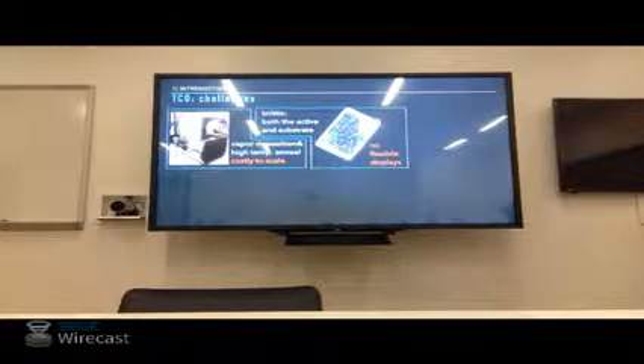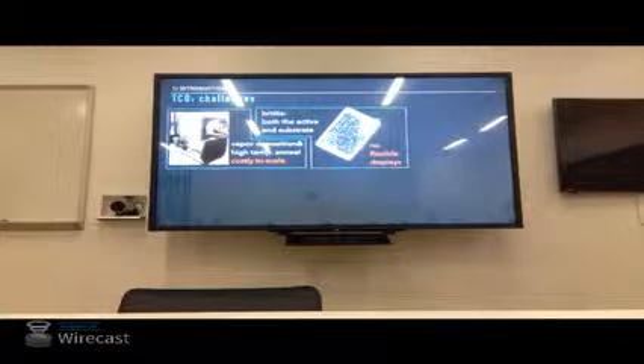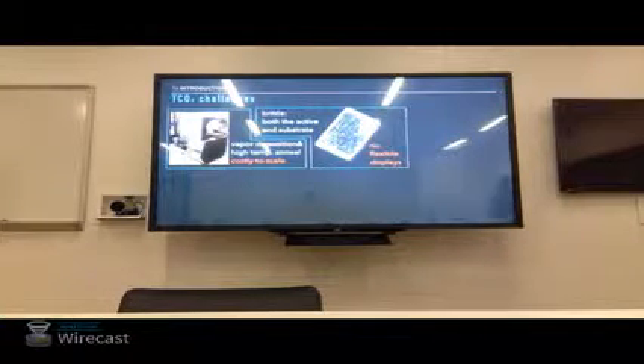As well, they're brittle, and this is mostly because, to have an excellent substrate for these things that handles high temperature and high vacuum and is inexpensive, we just use glass most of the time. The glass that's backing your transparent conducting oxide is one of the reasons why when you drop your phone, it does this. It shatters. It's one of the last materials in an optical display that is inherently brittle.